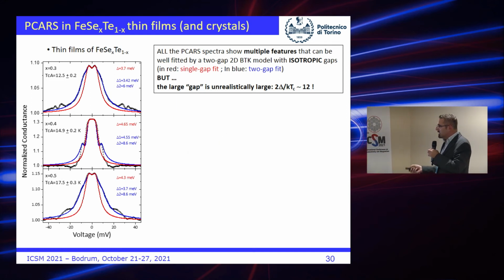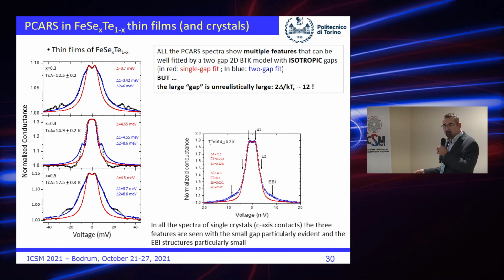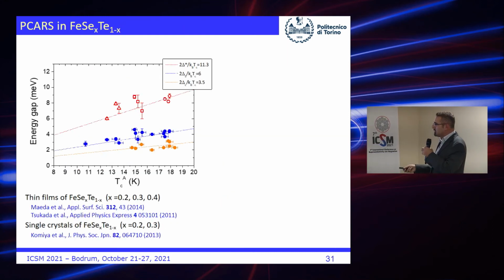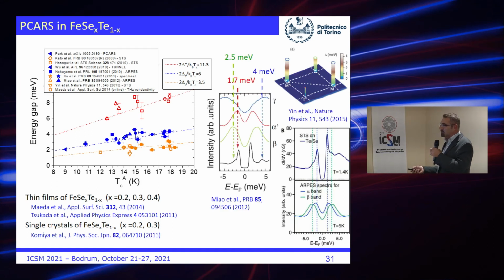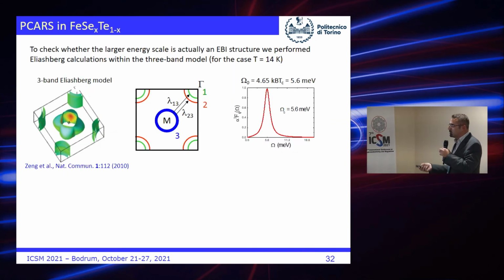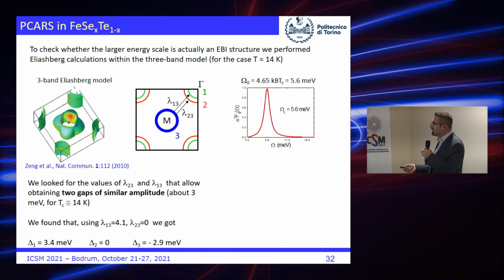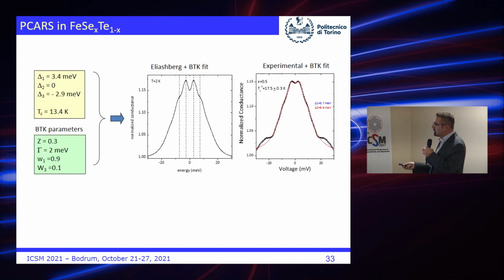So in the end, in crystals, even better, because the electron-boson interaction structures are well separated. We can do the same thing, so it turns out that these are the gaps, and this is the electron-boson interaction structure. That the fact that this is the real boson interaction structure is confirmed by using the same approach, and we can see that this is the curve generated within the Eliashberg theory. It is not made to fit a curve or an experimental one. It looks more or less like this one. And the fact is that this was generated with a gap of 3.4 and a gap of 2.9. So only this is the gap. These are electron-boson interaction structures.